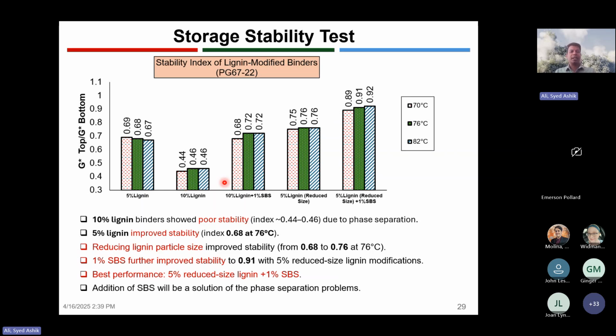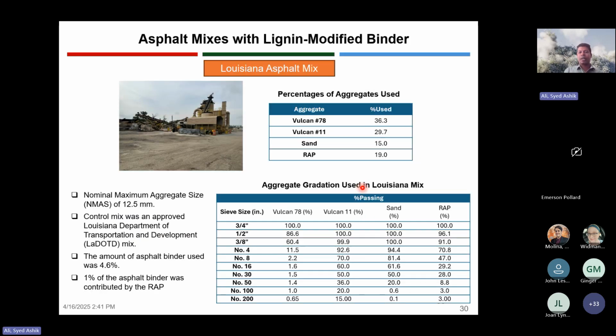For 10% lignin modification, though, the storage stability goes down so much that it is even difficult to get it back to the level that we want with the addition of SBS modification. But 5% did a pretty good job. Okay, so that was the end of the characterization of asphalt binder.